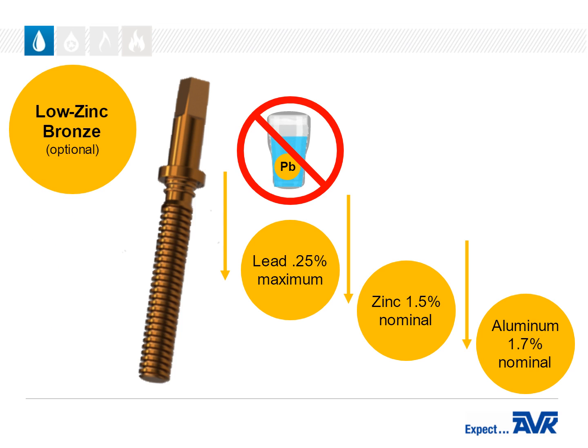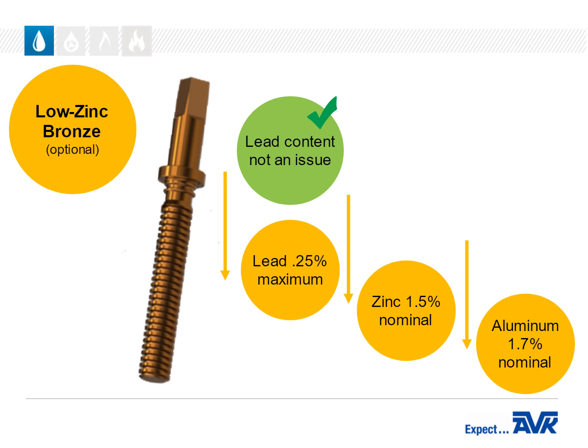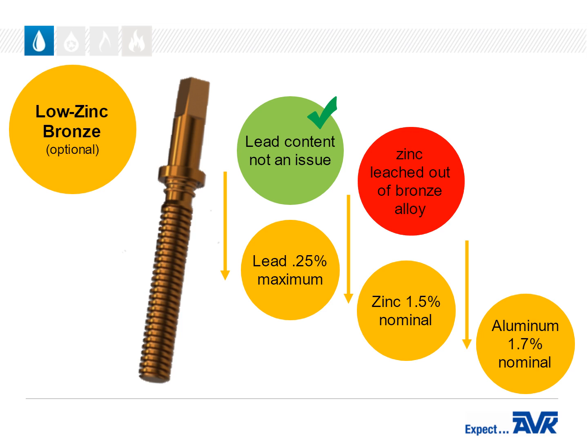Well, we all know that lead is not desirable in our drinking water. The EPA has mandated that the weighted average lead content in any valve intended for potable water contact be 0.25% or less. The AVK low zinc bronze stem easily meets this requirement. When exposed to water within certain chemistry and temperature ranges, bronze alloys with more than 15% zinc are affected by dezincification. Dezincification is the leaching out of zinc from the bronze alloy. With a zinc level of only 1.5%, dezincification is not an issue with the AVK low zinc bronze stem.